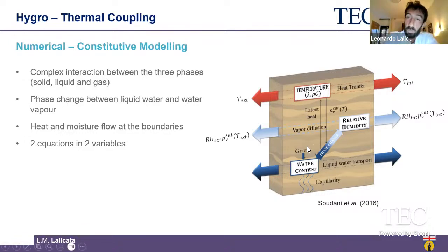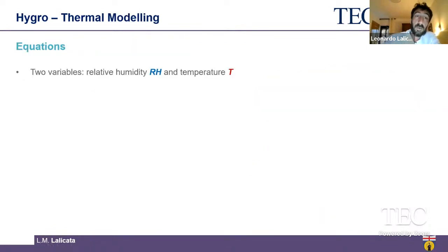And in these problems, we need also to account for the phase change between the liquid water and the water vapor that can go from one side to the other. We need obviously to account for the heat and moisture flows at the boundaries. And so in conclusion, we need to solve a system of two equations, one for the temperature and one for the water, in two variables. And these two variables are in general the relative humidity for the water and the temperature for the energy balance.